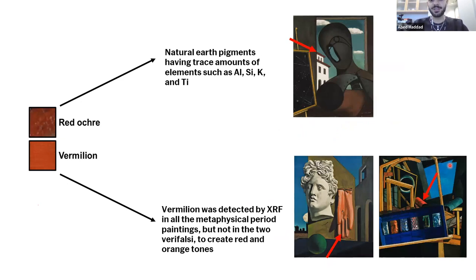For the reds, de Chirico listed four red pigments: morellone red, red earth, vermilion, and carmine lake. morellone earth, being a type of red ochre, can be difficult to distinguish from other kinds of red ochres, like a Venetian red, for example. They're all very similar in composition. They just have a different way of preparation. XRF identification of red ochre is less straightforward because you have to depend on the high levels of iron, quite often accompanied with other trace amount elements like aluminum, silicon, potassium, and titanium.